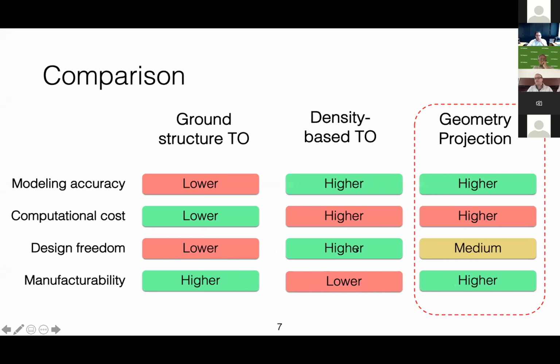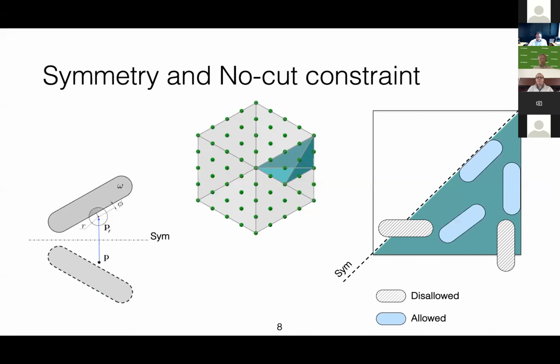We obviously don't have as much design freedom as density-based approaches because the lattice has to be made of these cylindrical struts, but we have more design freedom than ground structure approaches because the connectivity is not fixed. These bars can sort of move freely inside the unit cell. And because we end up getting open cell structures, they are easier to manufacture.